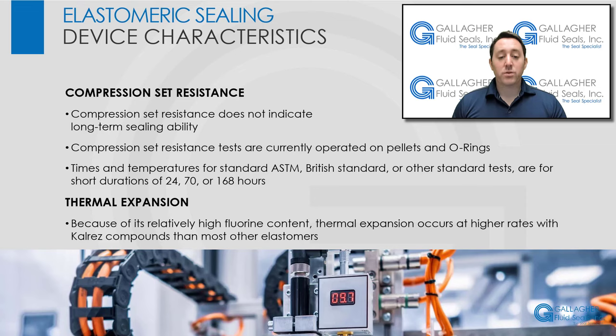Temperatures are chosen to reflect upper service temperatures of the elastomer type. This test can also be run in various media other than air. Because of its relatively high fluorine content, thermal expansion occurs at higher rates with Kalrez compounds than most other elastomers. This means that at extremely high temperatures, some changes or modifications in the sealing cavity design may be necessary to accommodate the increased elastomer volume.